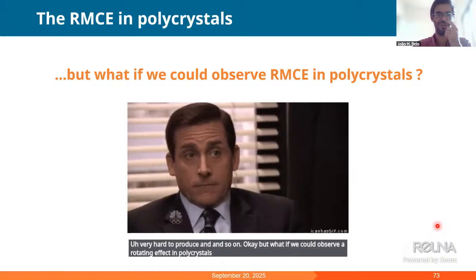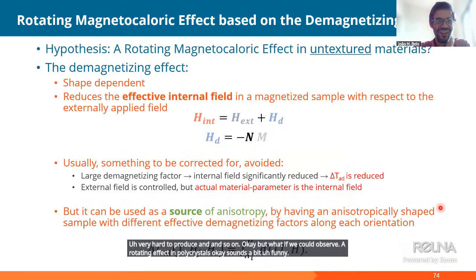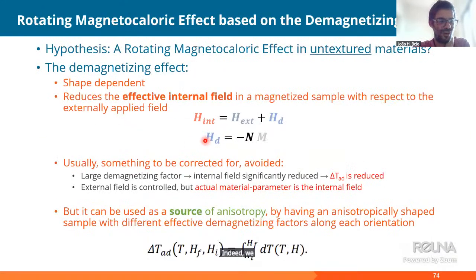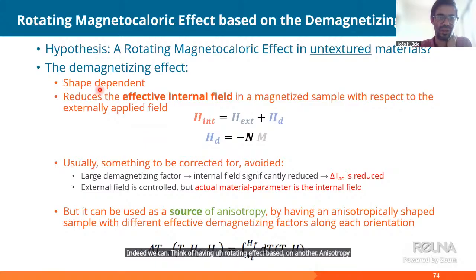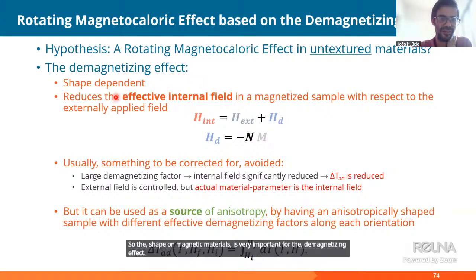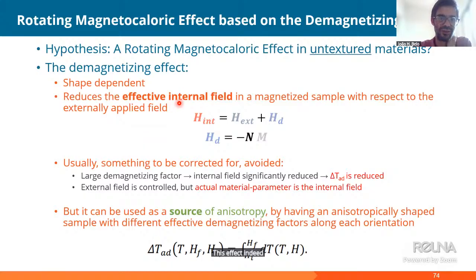Okay, sounds a bit funny. Indeed, we can think of having a rotating effect based on another anisotropy, which is a shape anisotropy. So the shape of magnetic materials is very important for the demagnetizing effect. This effect indeed reduces the effective internal field in a magnetized sample, in this way that can be seen here